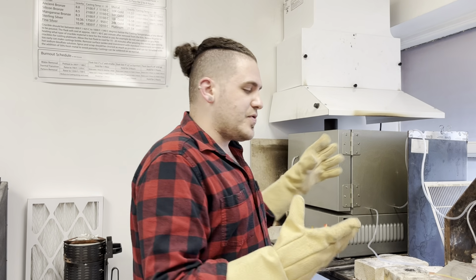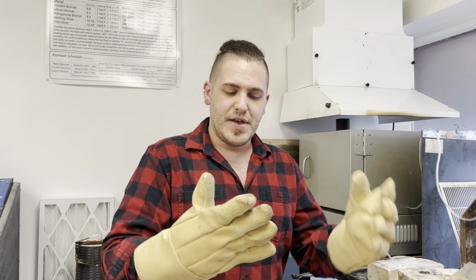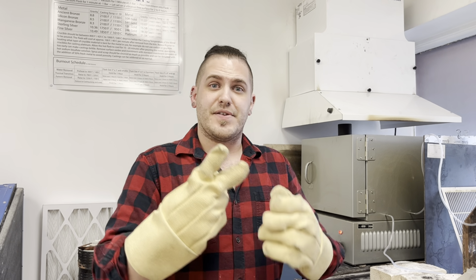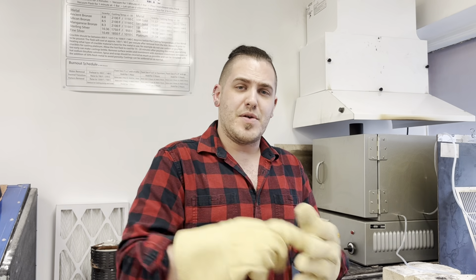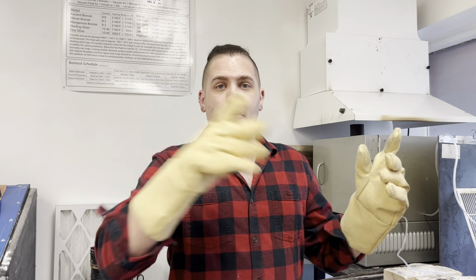We're gonna be making more videos on this topic if it's something that you guys are interested in. I can't imagine why you wouldn't be, because so far we've been able to cut our burnout time by more than half. So normally it would run about 12 to 14 hours, and now we're down to a very solid 5. We've also determined that we can invest our plaster in 2 hours instead of the full six hours. And mixing at a slightly lower ratio, the 36 to 100 versus 40 to 100, has pretty much eliminated any issues we have ever had with cracking and flashing. I think that's going to be very important whether or not you do a rapid or a long burnout.